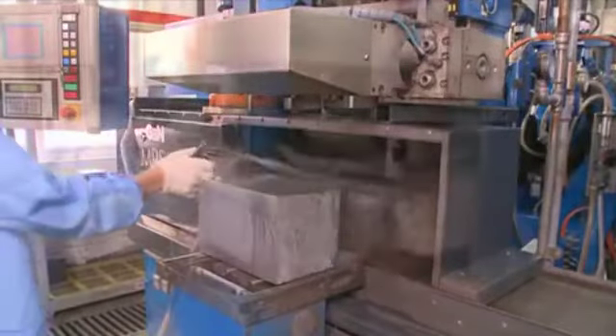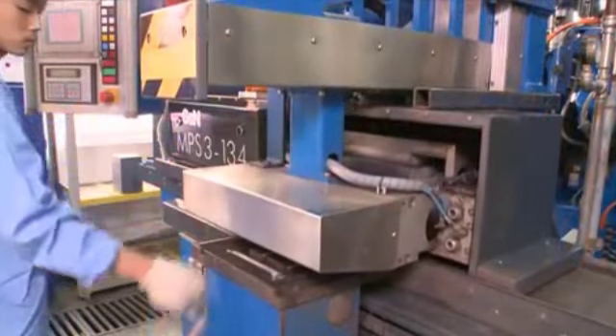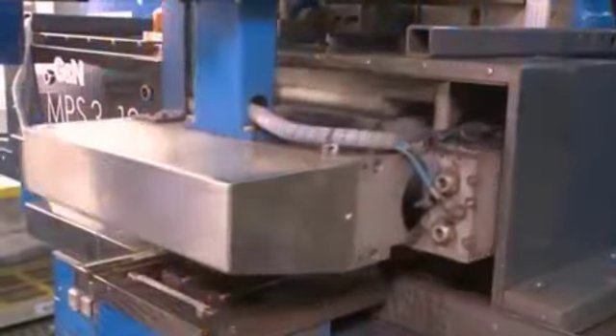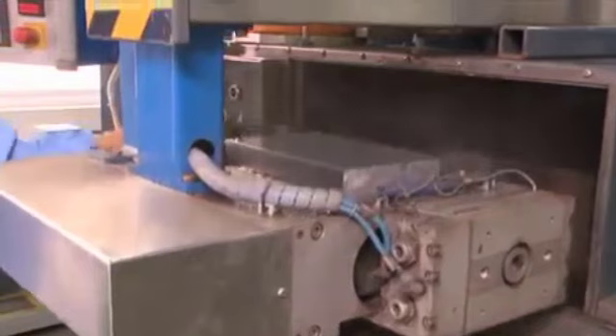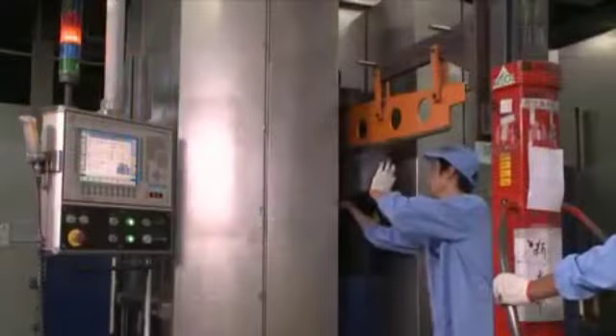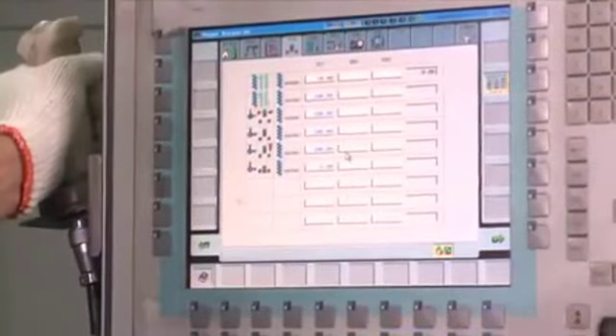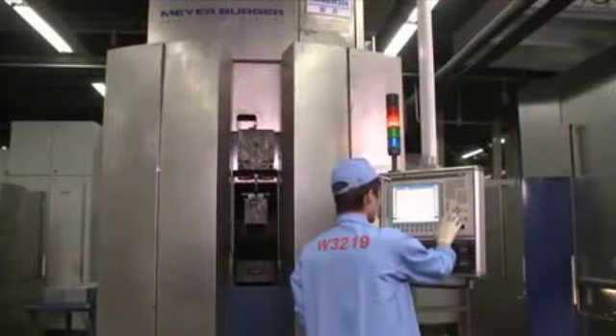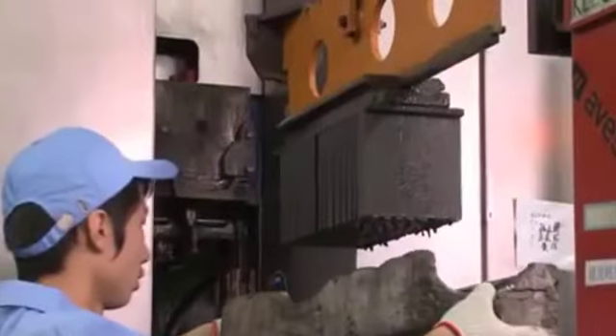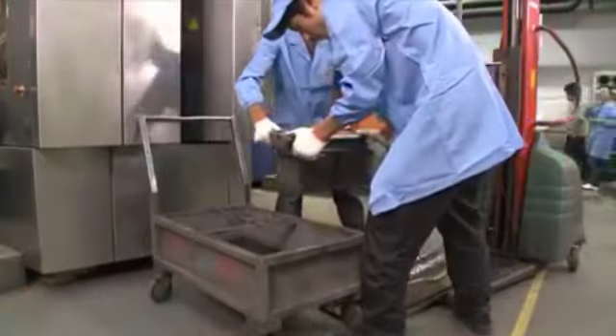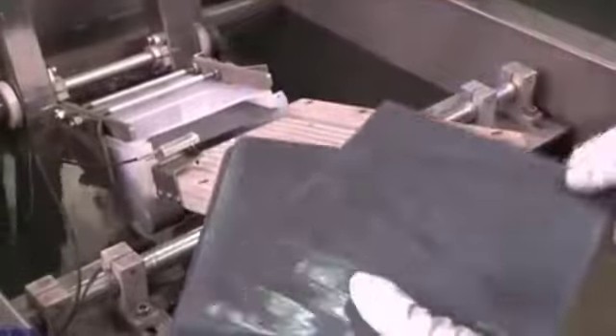To ensure maximum quality, the surface of the ingot is then polished and the edges are grinded. Finally, the usable parts of the ingots are sliced into wafers by wire saws using high-precision cutting techniques, which utilize steel wires and silicon carbide powder. After this process, the wafers go through a cleaning procedure to remove debris from previous processes.